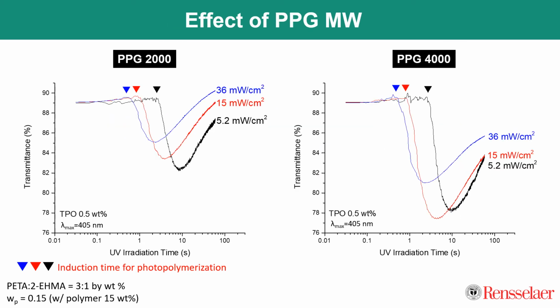So now moving forward, we can see that this still holds true if we look at one specific molecular weight. On the left here, we have PPG 2000 at the lowest UV intensity. We have the greatest extent of phase separation, and at the highest UV intensity, we have the lowest extent of phase separation, which is what I just mentioned on the previous slide, and we can see that it holds true as well with PPG 4000. Another thing to note is that these triangles here are denoting the induction time for photopolymerization, and as you increase the UV intensity, the induction time of photopolymerization as well as phase separation becomes quicker.